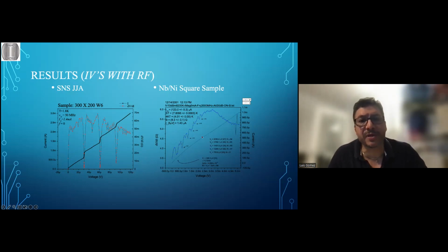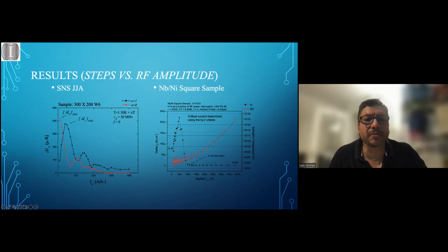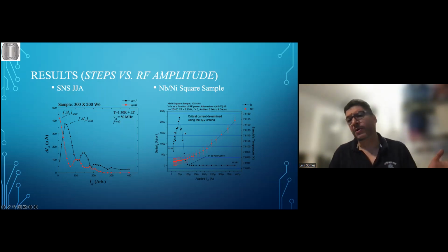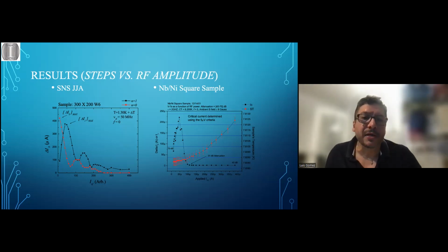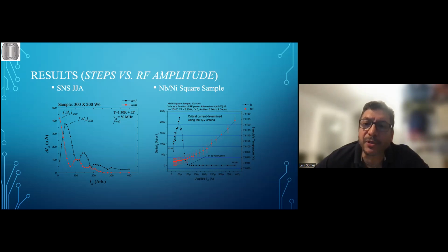But on the system with nickel, I was unable to see anything else but how the applied RF signal, the oscillating current, changes the critical current. So this only has N equals 0, but this one, I showed both N equals 0 and N equals 1. On the x axis, you have E_RF in arbitrary units. Is it the intensity of microwaves? Exactly. That's the amplitude of the microwave applied.